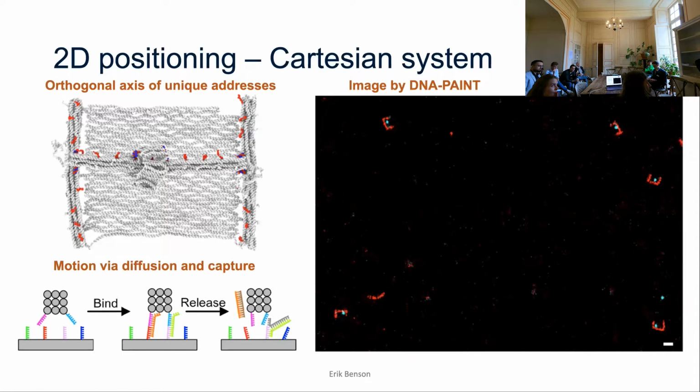Anyway, this is how we ended up imaging the final device. With DNA-PAINT, we choose what we image. We just image different DNA strands, and because we can program where the DNA strands come out of the structure, we can program what we image. In this case, it's set up with DNA-PAINT strands along these 2 beams, and then along a line on the canvas. That gets us a nice coordinate system. And then we also have orthogonal DNA-PAINT strands that we can image separately on the slider.